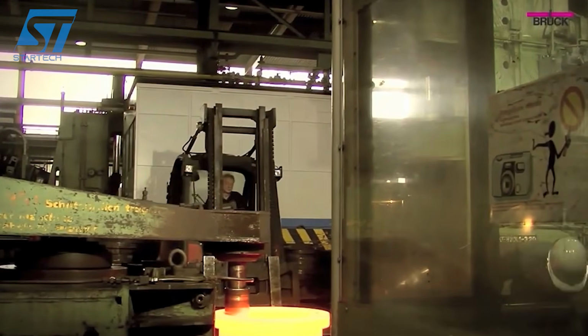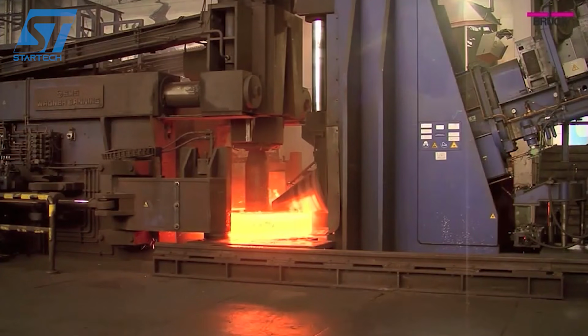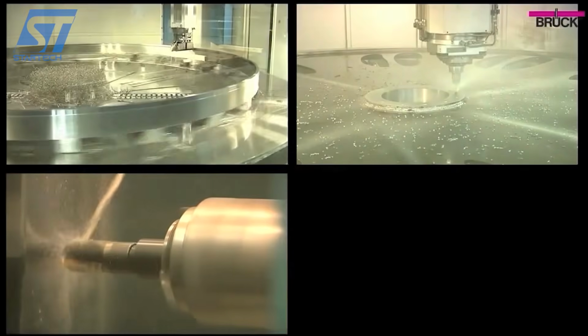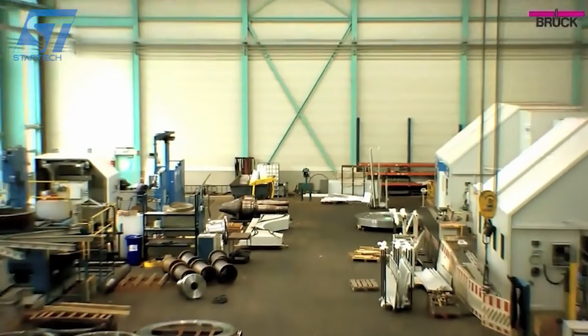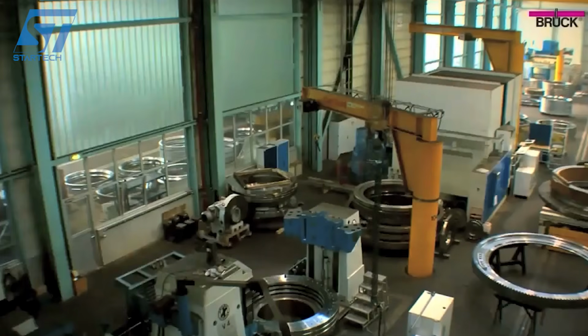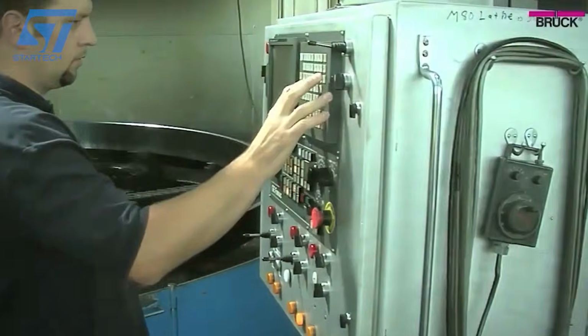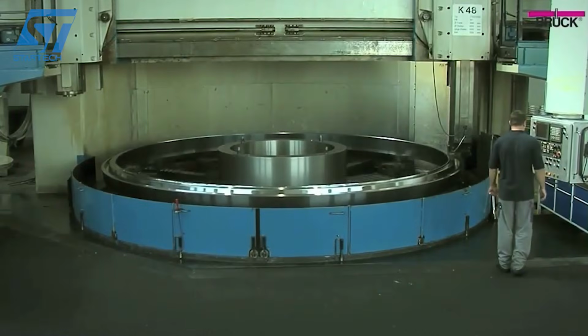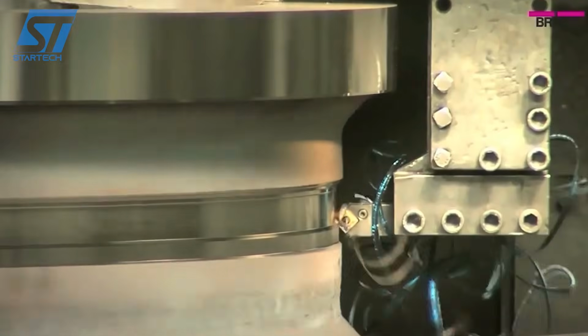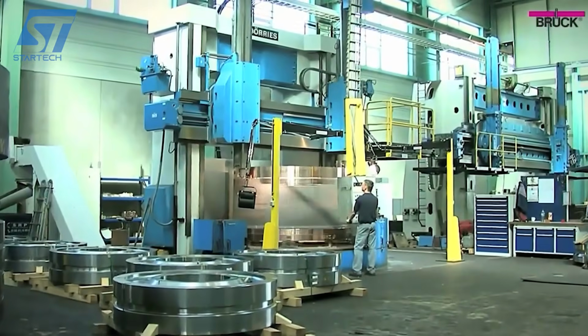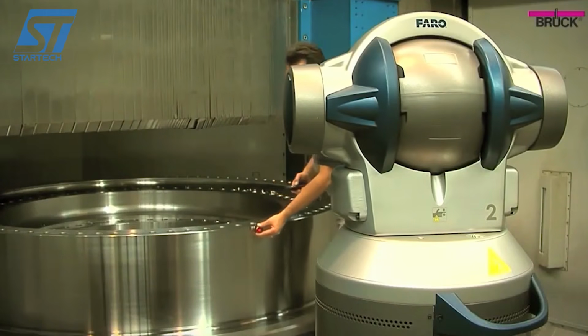Now comes the star of the show, the ring rolling mill. This is a purpose-built machine that looks like something between a lathe and a rolling press. The pierced blank is placed over a central mandrel roll, and a large main roll closes in from the outside. As both rolls rotate, they squeeze the ring's wall thinner and thinner, and because steel volume stays constant, the ring's diameter grows. It expands outward like a slow, glowing halo.